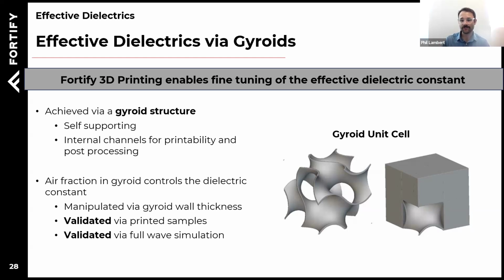And what we do here is we control the air fraction of this unit cell by controlling the wall thickness. And by controlling the wall thickness and thus controlling the air fraction, we can thus control the effective permittivity. And I'll go into that in a follow-up slide.